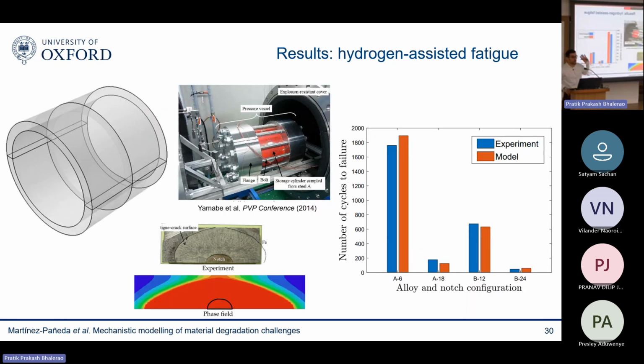And by the way, we have not only done fatigue calculations for lab scale tests, but also full scale tests. These are tests that were done by a Japanese group, and they tested full pressure vessels with different notches and different materials. And you can see that the number of cycles to failure predicted by the model and by the full real scale experiments seem to be in good agreement. So we were quite excited, because if you can capture fatigue, then all the other problems become kind of toy problems.